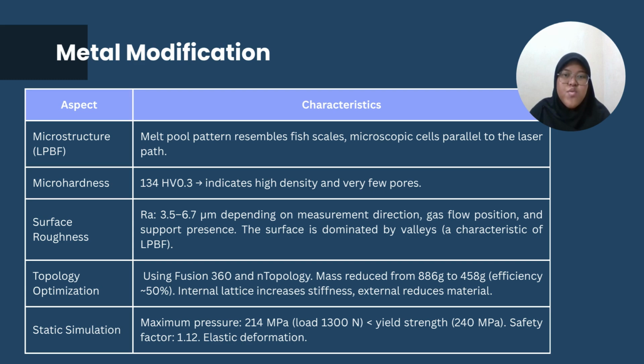And number four is topology optimization. The mass was reduced to 458 grams by using an internal lattice structure to maintain rigidity while reducing material usage. And the last is static simulation. The maximum pressure of 214 MPa is below the yield strength of 240 MPa with a factor of safety of 1.12, indicating elastic deformation.